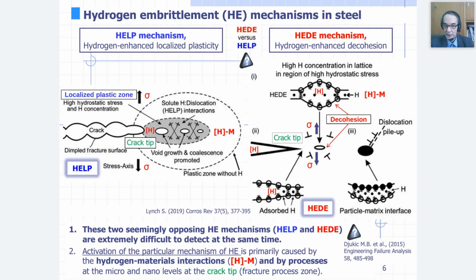Just briefly about the HEDE mechanism, which is a completely different type of mechanism. We have a high accumulation of hydrogen, which provokes decohesion, which means that we have a drop in cohesive strength of the material due to accumulation of hydrogen at particular trap sites, like the particle matrix interface, like some pre-existing void, like grain boundaries. As you can see, hydrogen promotes the decohesion of the grain boundaries. These two seemingly opposing mechanisms: HELP promotes enhanced plasticity, while on the other side HEDE talks about real embrittlement, like in the name of the effect, hydrogen embrittlement of material.